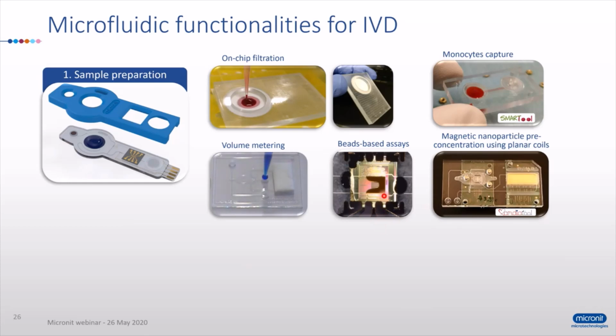microfluidics using different approaches. This first example uses polystyrene beads that are coated with antibodies against ELISA products. They were used for a bead-based ELISA, and they were captured inside this channel. The channel in this case was a glass channel, 700 or 800 micrometers wide and only 8 micrometers deep. And a filter, a sort of mechanical barrier, was fabricated inside this channel, leaving only a 1.5 micrometer gap, so that the beads could not escape and would be trapped, while the liquid sample, without the analyte of course, would leave the microfluidic chamber. And in this case, the beads are facing a sensor. I will get back to that in another slide.